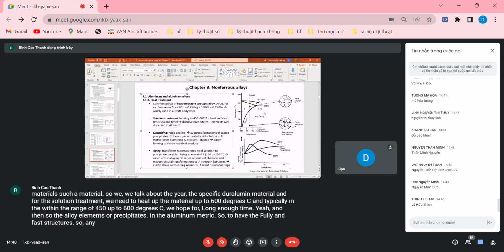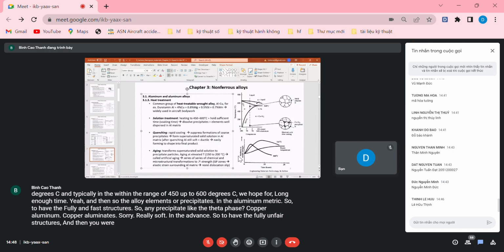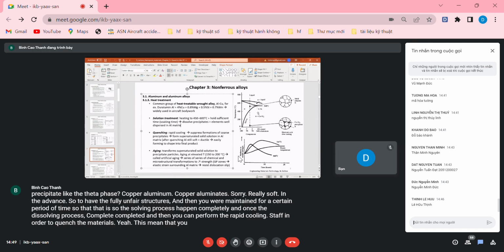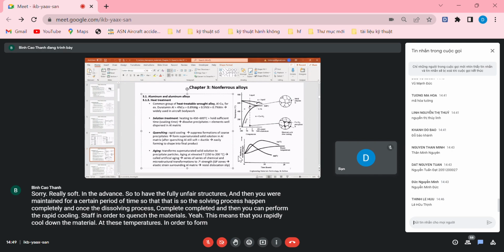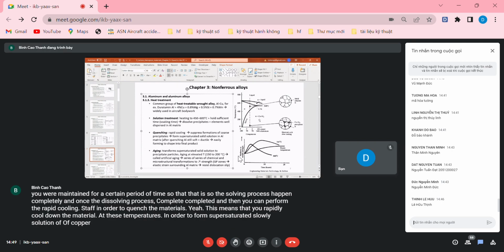So any precipitate like the theta phase, copper aluminide, will be dissolved, to have the fully single phase structure. And then you maintain for a certain period of time so that the dissolving process happens completely. Once the dissolving process is completed, you can perform the rapid cooling step in order to quench the material. This means that you rapidly cool down the material from these temperatures in order to form a supersaturated solid solution of copper inside the aluminum matrix.